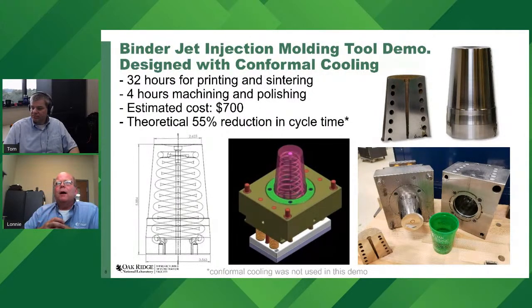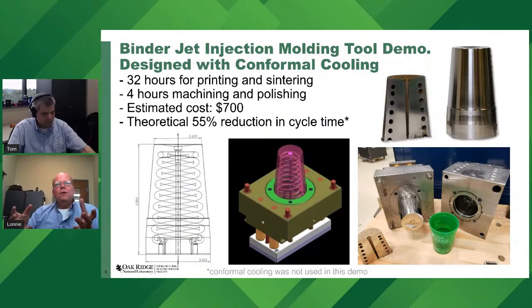Now again, great application is tooling, where you need to do like conformal cooling. This was a binder jet project that Amy had to make a core for an injection mold cup, and you could actually do these cooling lines. This is the beauty of additive. You can have very complex cooling lines so that you can circulate the fluid, get really good heat transfer. You can print it near net shape, then you bake it, then you densify it, and then you do your final machining.